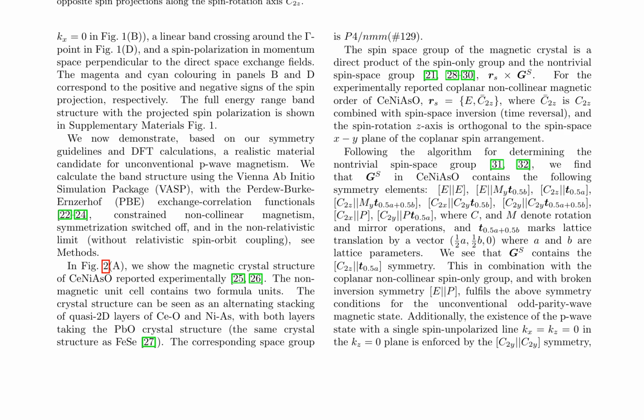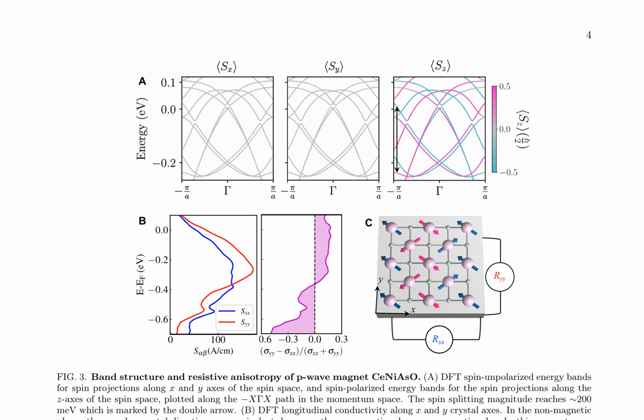CeNiAsO fulfills the symmetry conditions for an unconventional odd-parity wave magnetic state, with broken inversion symmetry, E, P, and the existence of the C2z, T0.5a symmetry. The full energy range band structure with the projected spin polarization is shown in supplementary materials Fig. 1. The band structure and resistive anisotropy of p-wave magnet CeNiAsO are presented in Figure 3.